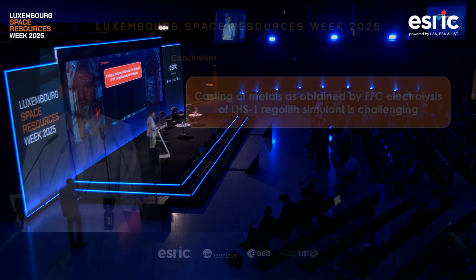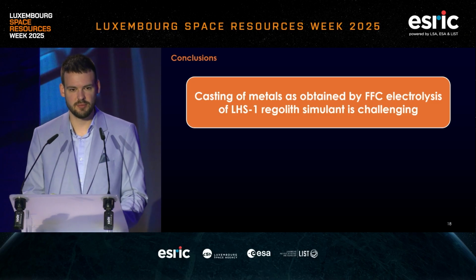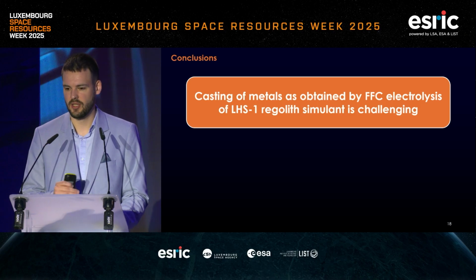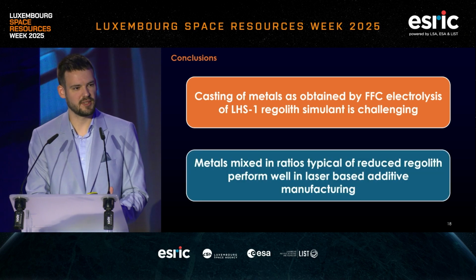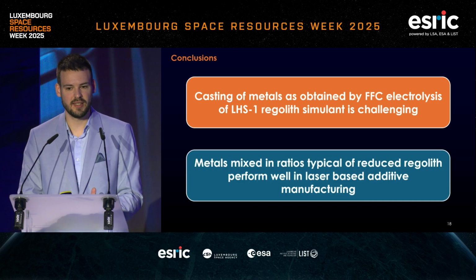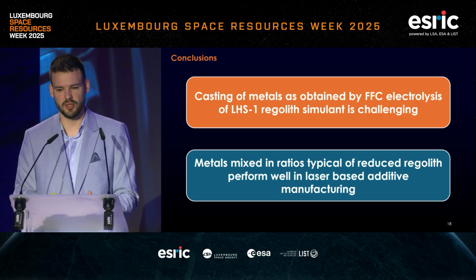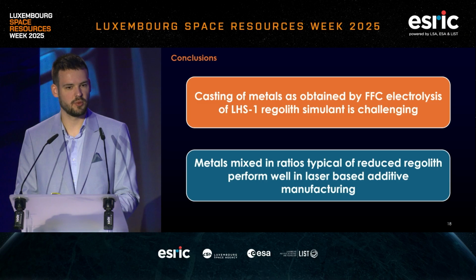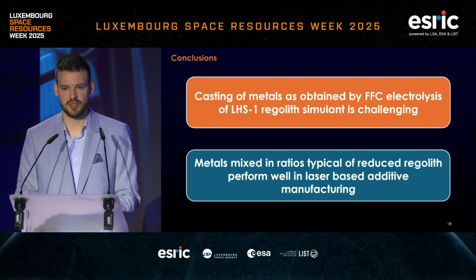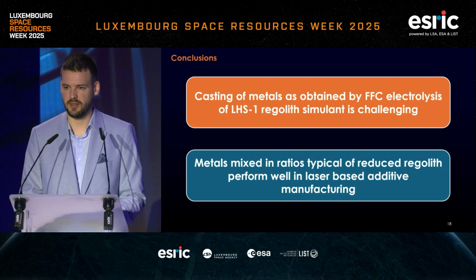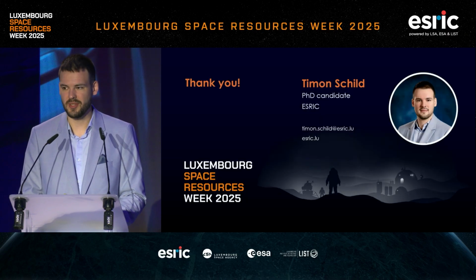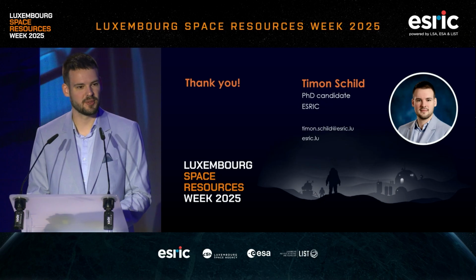So the 2 conclusions I'm taking from this work, first of all, the melting behavior of the metals that come directly out of the FFC process is not trivial and still needs some work. Our suspects, as I said, are residual oxygen content or contaminants from the process. But if we can solve this step, the metal ingots we are expecting to get at the end of this work actually should be quite suited to the wire laser-based additive manufacturing process, especially if we get a very nice melting behavior. I'm going to leave with that. Thank you very much for your attention, and I'm happy to take some questions.